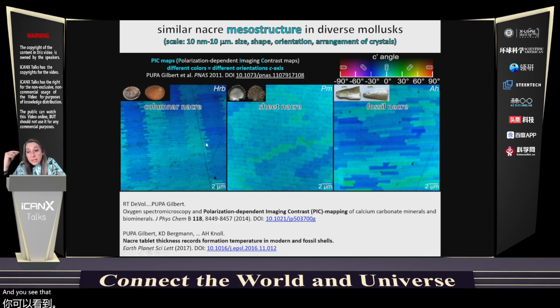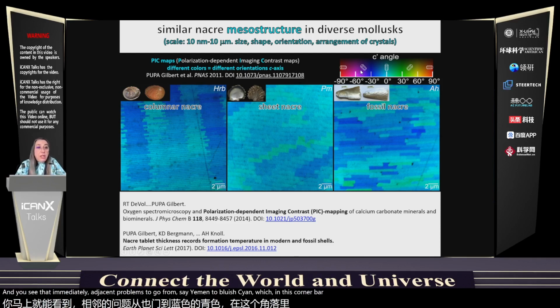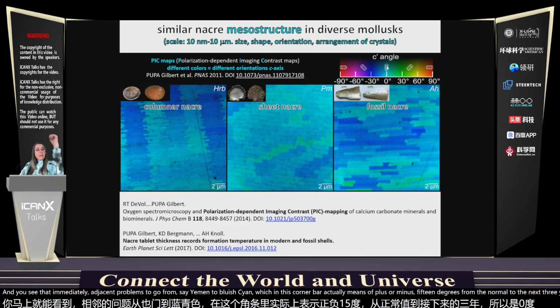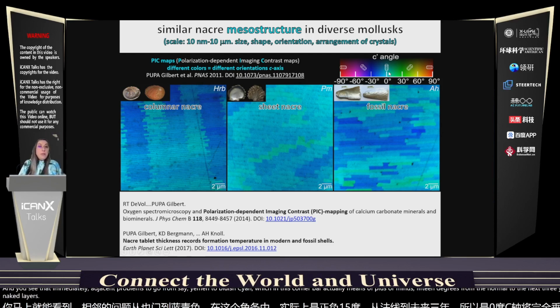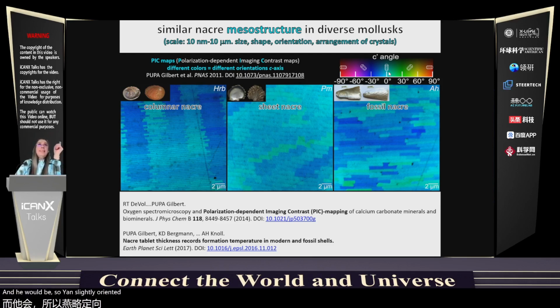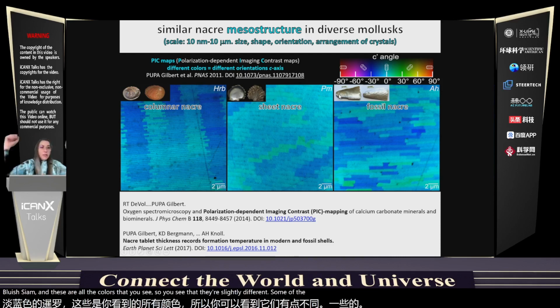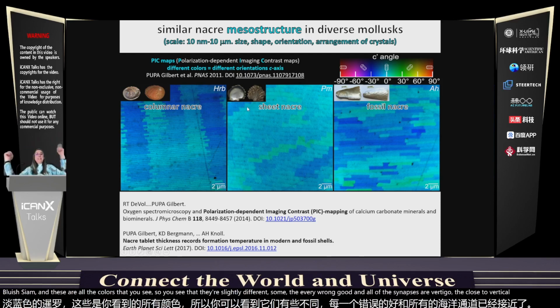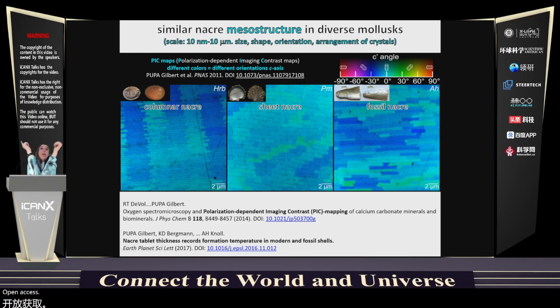And you see that immediately adjacent tablets go from cyan to bluish cyan, which in this color bar actually means plus or minus 15 degrees from the normal to the nacre layers. So a 0 degree C-axis would be perfectly perpendicular to the nacre layers, and it would be cyan. Slightly oriented towards, let's say, not quite 1 o'clock, but 12:30, halfway between noon and 1 o'clock, this would be plus 15 degrees, greenish cyan. At 11:30, it would be bluish cyan, and these are all the colors that you see. So you see that they're slightly different. It's not very wrong that all of the C-axes are vertical. They're close to vertical, but they can actually be within a cone of aperture 30 degrees.